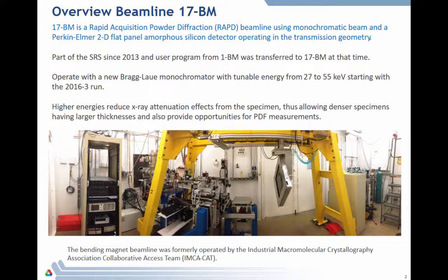We installed a new monochromator in station A a couple of months ago. It's a new Bragg-Laue mono, which allows us to easily change the energy between 27 and 55 keV. These high energies will allow us to do samples with higher absorbance and thicker samples, and of course a wider range of sample environments.